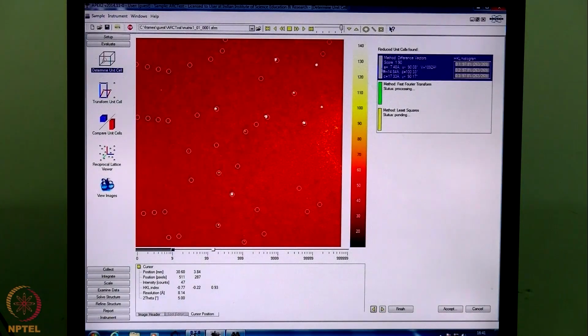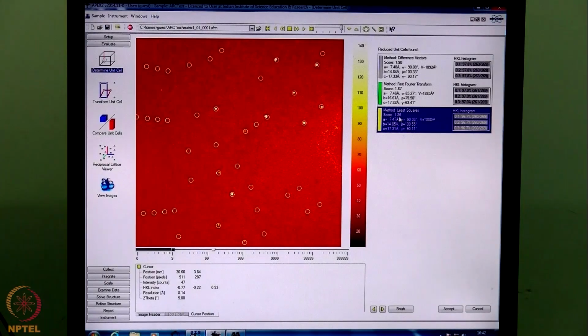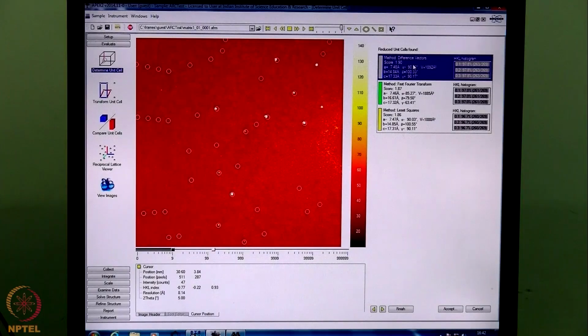Initially it gives a monoclinic unit cell with 90.08, 90.17 and 100 beta. This is a triclinic unit cell. This is again a monoclinic unit cell. You see that these 3 are of about the same volume: 1888, 1885, 1892. So one should take the higher symmetry cell, which is a monoclinic cell, probably the blue one, and the other one, which is here, has a score of 1.86. Here the score is 1.90, which indicates it is slightly better than that.